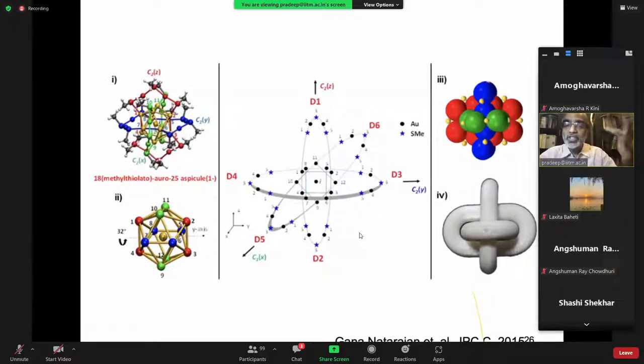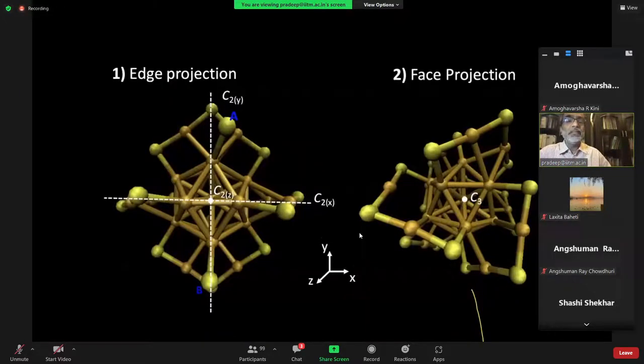Now, this structural insight is obvious from that ring-in-ring model called the Borromean model. This is one such three-ring structure. This is common in Eastern philosophy, and that is a chemical bond. If you break this chemical bond, this ring will come out and the two other rings will come out too. So one chemical bond breaking breaks this structure completely. And that assembly and disassembly could be the reason for these clusters to get formed. And we call this the aspicule nomenclature. Aspis is shield and cule comes from molecule, so these are actually shielded molecules.